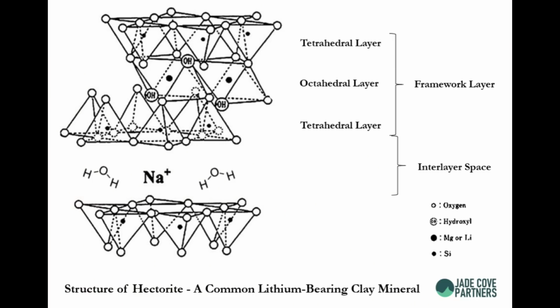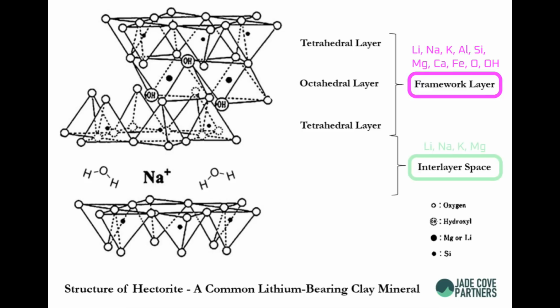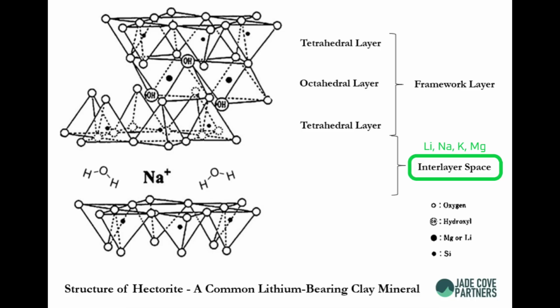To get a better understanding of the differences between lithium clays, we need a general understanding of how they're structured at the atomic level. The lithium in lithium clay can be held in two places, in the framework layer or the interlayer. If the lithium is contained in the framework layer, it's more difficult to extract because the lithium is actually part of the crystal structure. If the lithium is contained in the interlayer space, then it's much easier to remove because it's not contained within a crystal structure. These crystal structures are not all identical, and the specific chemical makeup of the crystal structure can dictate the extraction process. The framework layer can include elements such as lithium, magnesium, aluminum, silicon, and oxygen. The interlayer can include positive ions such as lithium and magnesium.